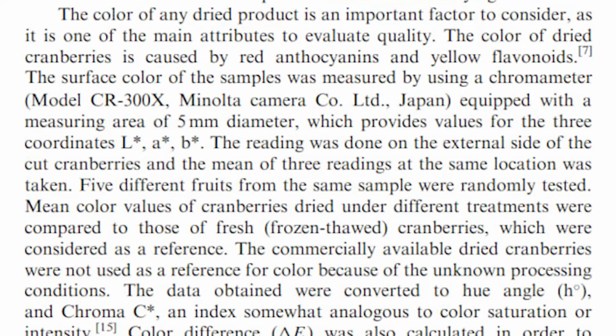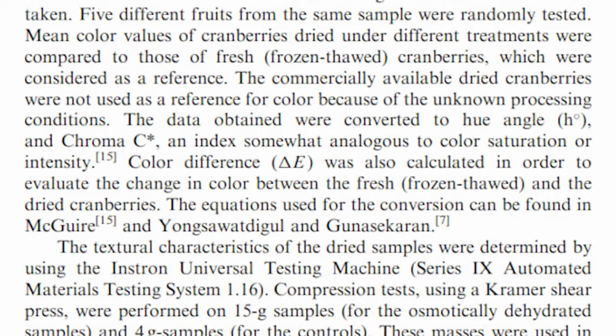The color of any dried product is an important factor to consider, as it is one of the main attributes to evaluate quality. The color of dried cranberries is caused by red anthocyanins and yellow flavonoids. The surface color of the samples was measured using a chromameter, model CR-300X, Minolta Camera Company Limited, Japan, equipped with a measuring area of 5 mm diameter, which provides values for the 3 coordinates: lightness, L, redness, a, and yellowness, b. The reading was done on the external side of the cut cranberries, and the mean of the 3 readings at the same location was taken. 5 different fruits from the same sample were randomly tested.